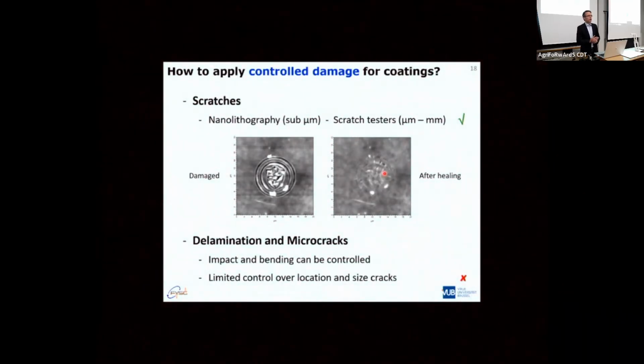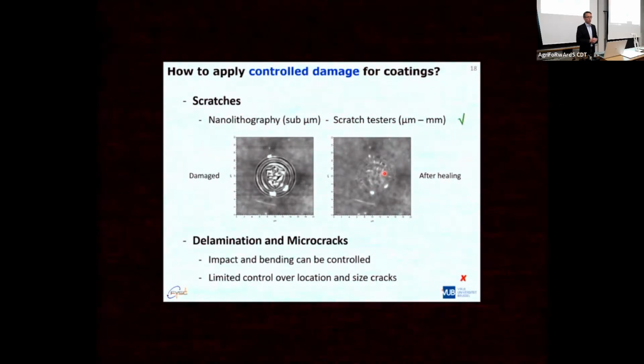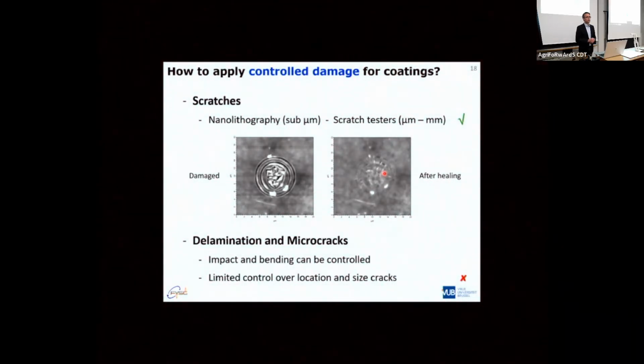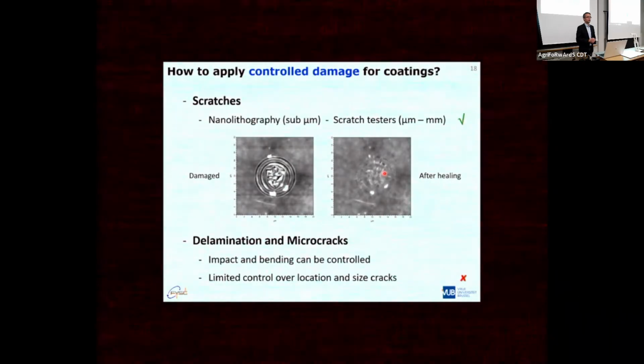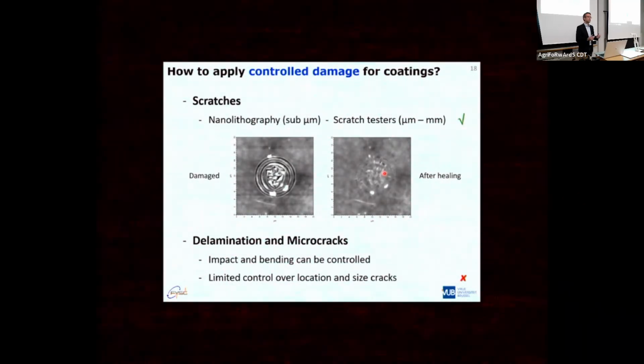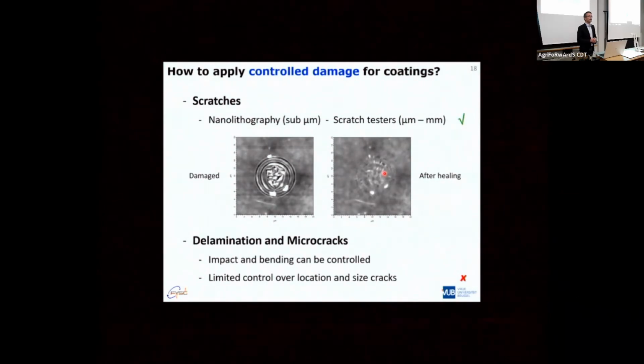For delamination and microcracks, typically things like impacts and bending tests can be done to create these damages, but they will give you a limited amount of control over the location and over the size of the cracks or the damages that you are making. So it's not a very controlled test. You can go to ASTM or ISO to look up the conditions under which to do it. So the source of the damage is the same, but the result will be very different from sample to sample even, but certainly also from material to material.